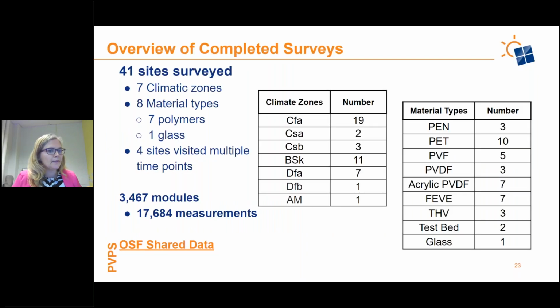So we ended up measuring 41 sites in 7 different climate zones. We ended up identifying 7 different polymers, and we ended up at a site once with glass backsheets. And at 4 sites, we were able to measure multiple time points so that we got a temporal aspect. And in all, we have over 17,000 measurements, and all our data is publicly available on OSF. And we're willing to accept other individuals who want to do field survey and add to our database.